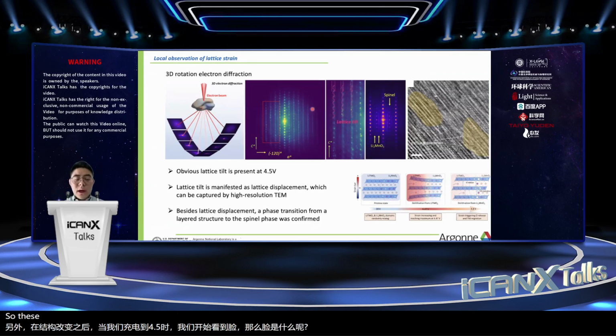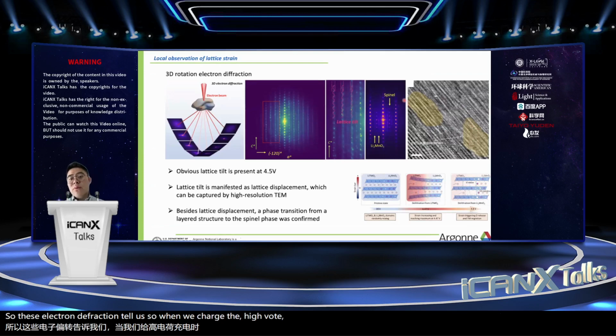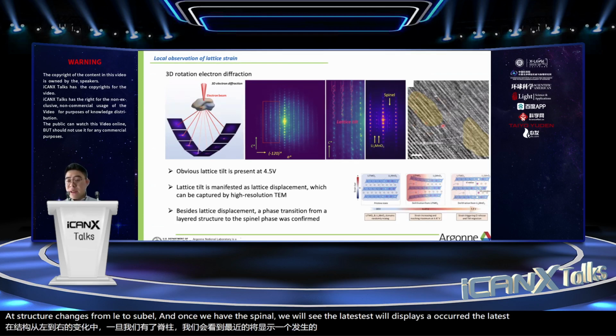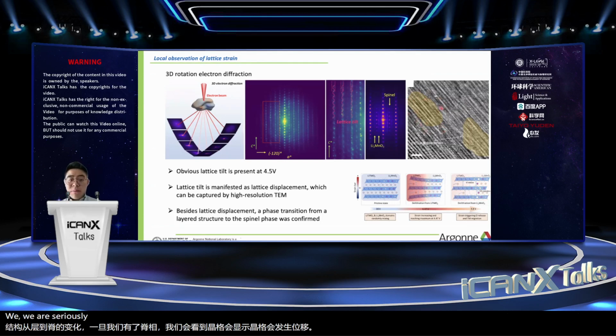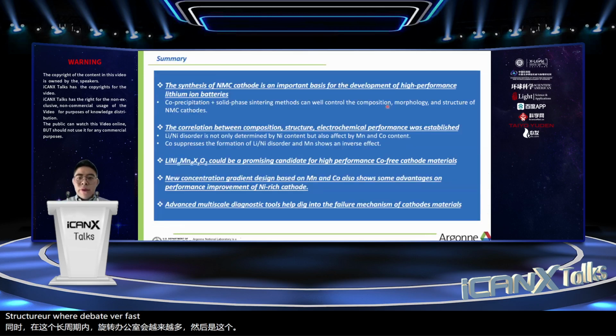So this electron diffraction tells us that when we charge to high voltage, we start to see the structure change from layered to spinel. Once we have the spinel phase, lattice displacement occurs very seriously inside the particle bulk. Also, over long cycling, the spinel phase grows more and more, and then the structure degrades very fast. So now I'd like to summarize my presentation.